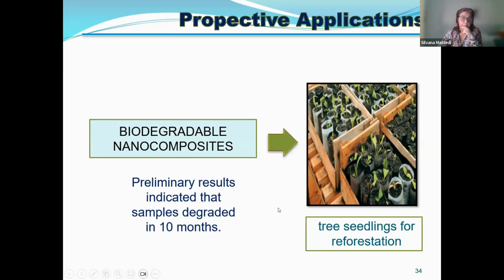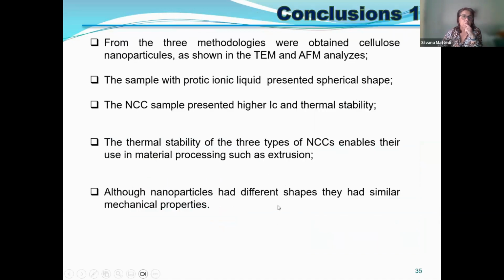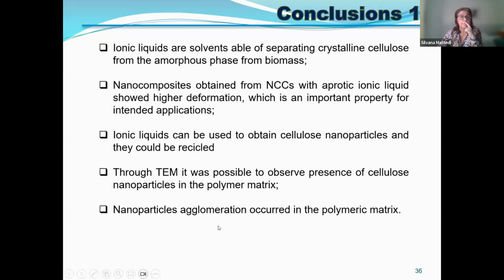Now we have the conclusions for this part. We tested the three methodologies, and we obtained cellulose nanoparticles with all of them. The sample with protic ionic liquid presented spherical shape. The cellulose presents higher crystallinity and higher thermal stability, but the thermal stability of the three materials could allow use in extrusion, though we have to test it, because after the material is extruded. And although the nanoparticles had different shapes, they had similar mechanical properties.